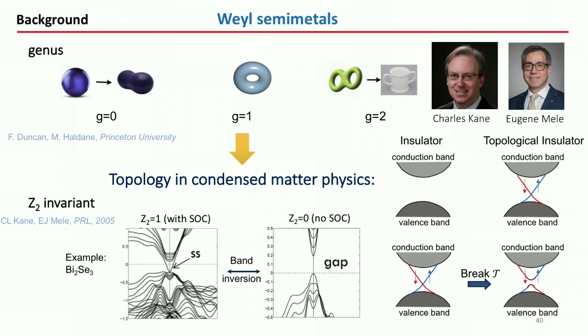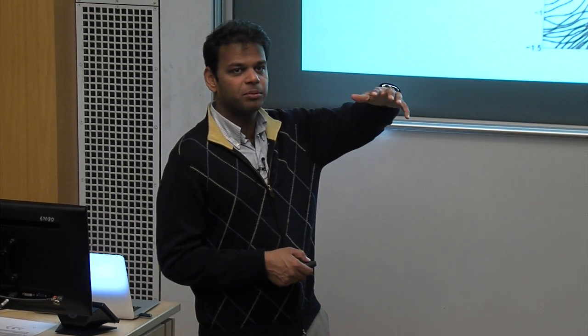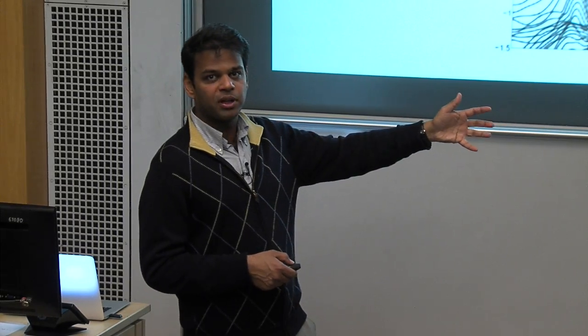The same thing happens in, this started from the quantum Hall effect. People realized you can describe electronic states by these topological invariants. And what happens in topologically non-trivial systems is that because of the presence of strong spin-orbit coupling, there is this natural ordering of bands. For example, in most semiconductors, the valence band is made up of p orbitals, the conduction band is made up of s orbitals. But because of strong spin orbit coupling, you change the ordering. So that gets associated with a particular genus or topological invariant.